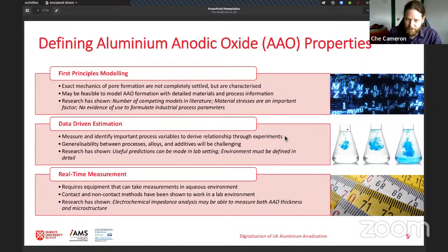Of particular interest that I'd highlight is electrochemical impedance analysis, where essentially you inject a signal into the structure, and from that you can tell potentially an awful lot about both the microstructure and the thickness. Microstructure is interesting because generally if you want to find out about that pore morphology in detail, you must use a scanning electron microscope. And for obvious reasons, most anodization operators do not have a scanning electron microscope on the shop floor.